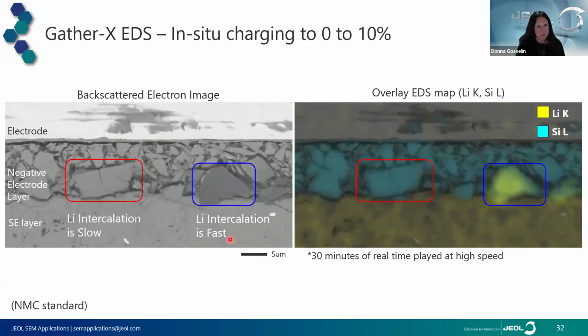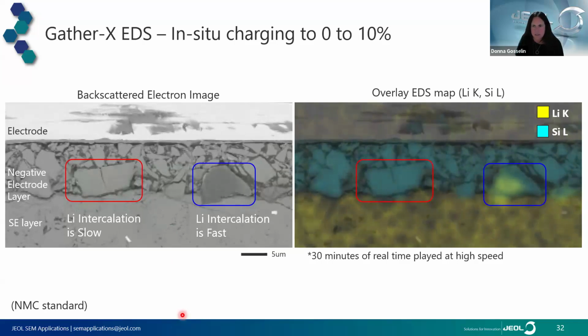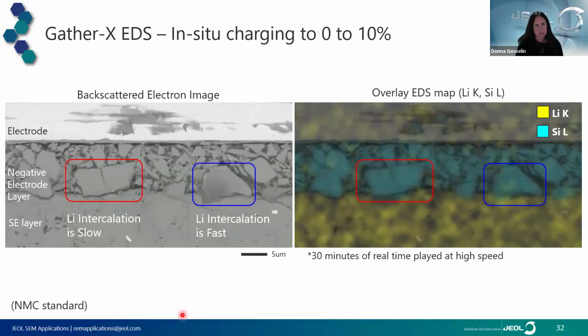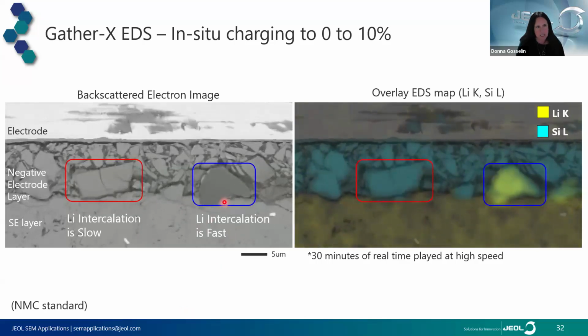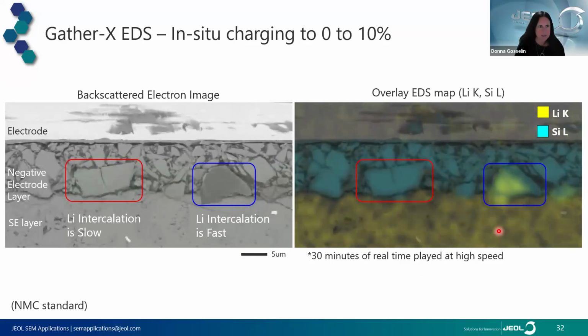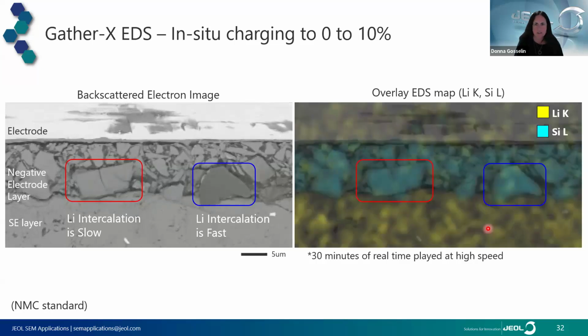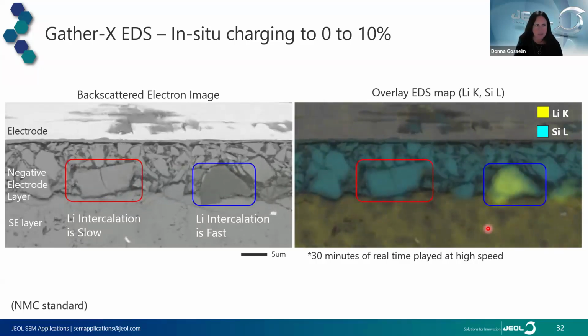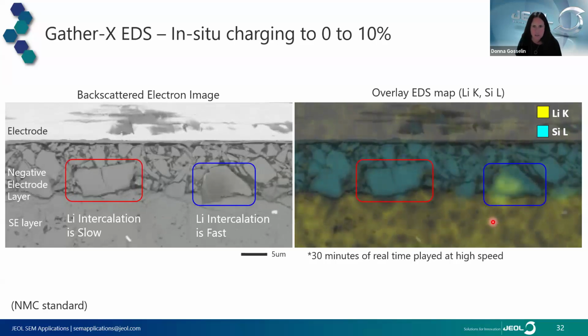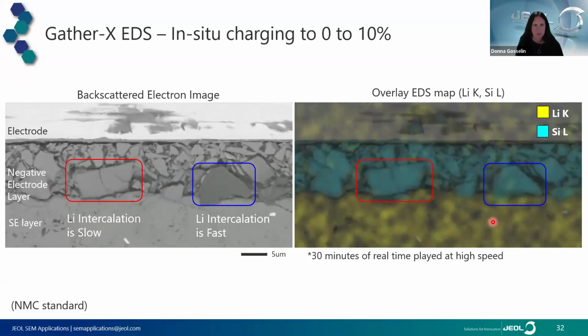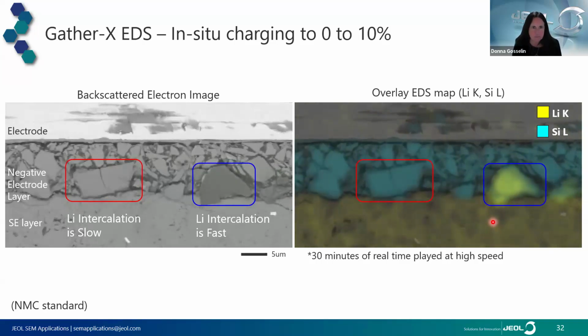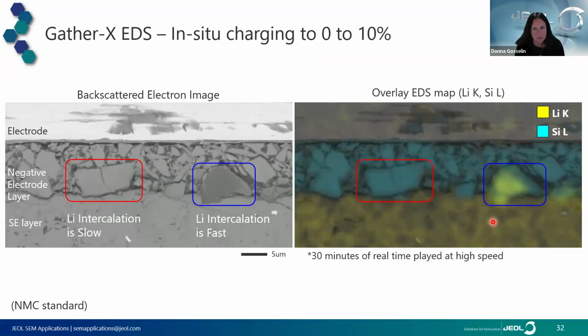And you can see there's differences in how these particles behave. We're going to focus on the particle here on the right-hand side. And during this time, you can see from the backscatter electron image, it's changing in contrast. It gets a little bit darker. And we have an overlay of the lithium K and silicon maps on this image. We can observe, in particular, this particle that's highlighted on the right, that the lithium is intercalating gradually into the silicon particle. This one is closer to the interface with the electrolyte. So maybe that contact allows for a quicker intercalation of the lithium into the negative electrode.